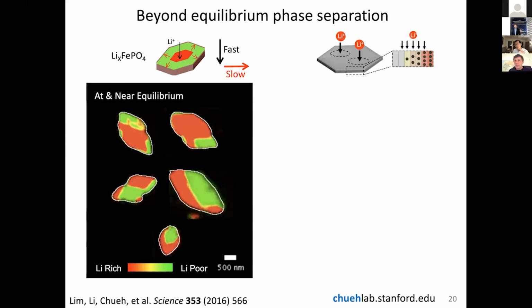Now, let me zoom in to one particle. As I mentioned, lithium iron phosphate has a very large miscibility gap. So if you take a composition that is right in the middle of the gap, say lithium 0.5 iron phosphate, so half filled, and you let phase separation happen, then you can observe the phase separation using microscopy. This is work done using X-ray microscopy, showing lithium-rich and lithium-poor phases, where red is lithium-rich and green is lithium-poor. Lithium iron phosphate has a one-dimensional transport path, and the elastic requirements will have the boundary in a certain anisotropic direction. So you see these beautiful domains of lithium-rich and lithium-poor domains.